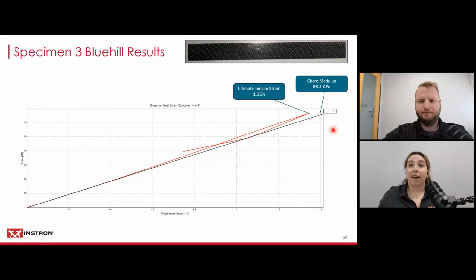And then lastly, that largest specimen, which broke just above 60 kilonewtons, we have a little bit of negative strain occurring because of how high of an impact that break was. So it's a little risky that I left it on till the end of break, but I did capture the correct ultimate tensile strain that aligns with my max force. So this is another instance where I could probably remove it earlier in the test and let that crosshead displacement take over. And then our chord modulus for this one looks good at 66.3 gigapascals.